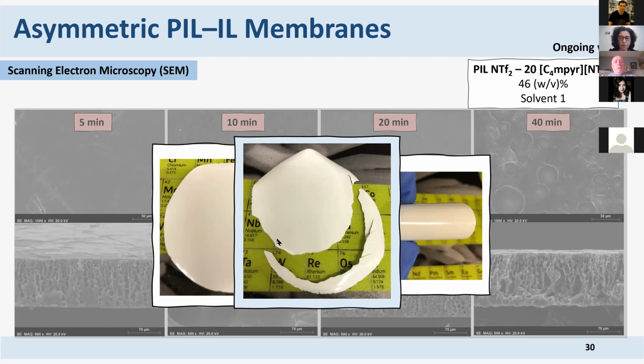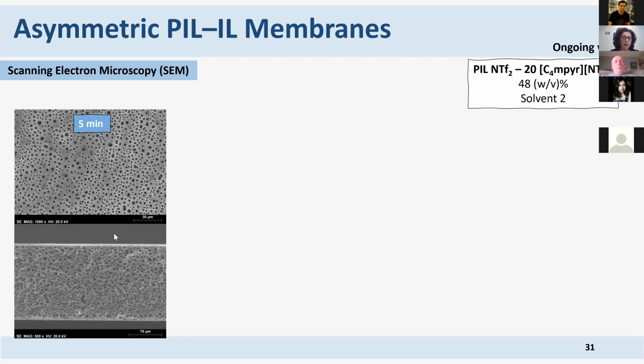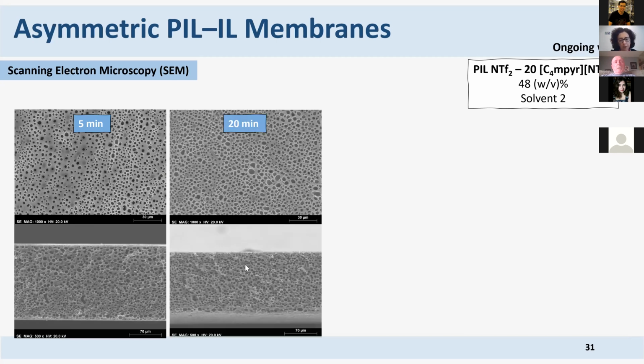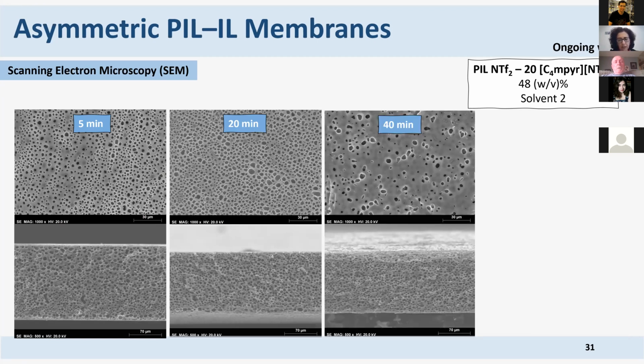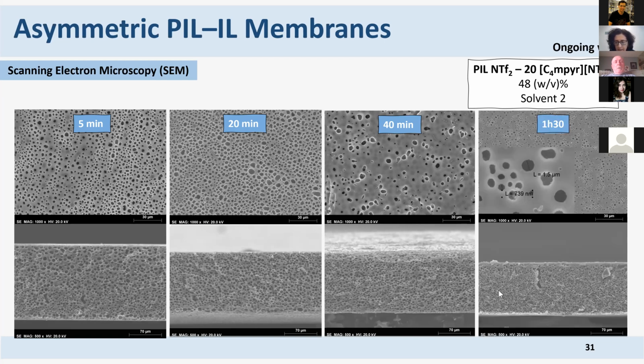What happens with solvent 2? With solvent 2, it's quite different. So you see here, after 5 minutes of evaporation, the top layer is porous and the morphology is sponge-like. And if we leave it for 20 minutes, we continue in the same situation, and for 40 the same, but now the pores are becoming smaller, and here the pores are much smaller. And we still maintain the sponge-like morphology inside of the membrane. Here the pores go from 500 nanometers to 1.6 micron.